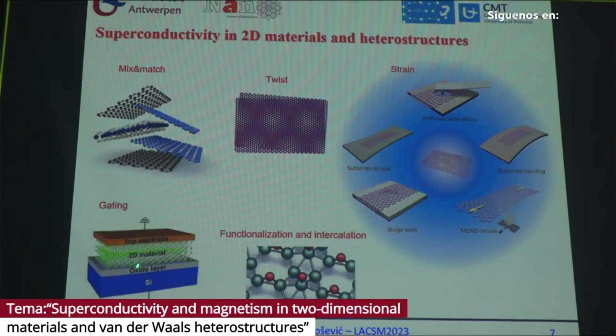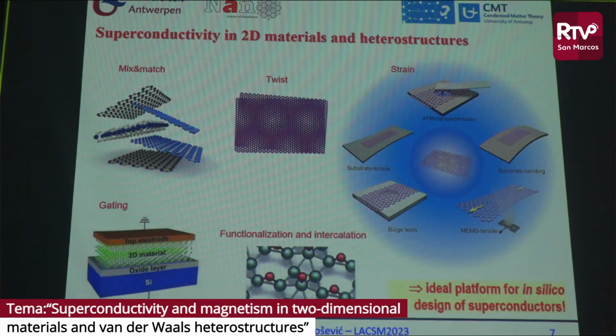Gating: because the materials are ultra thin, very small voltages will lead to very large electric fields, and very large electric fields can modify the properties of your material dramatically. Right now, I think the record field is about 3 volts per nanometer. And anybody doing calculations will know that that kind of field completely changes the electronic properties of the material. Two-dimensional materials are prone to functionalization and intercalation, so we can functionalize them with different types of adatoms. And altogether, this makes 2D materials an ideal platform for computational design.